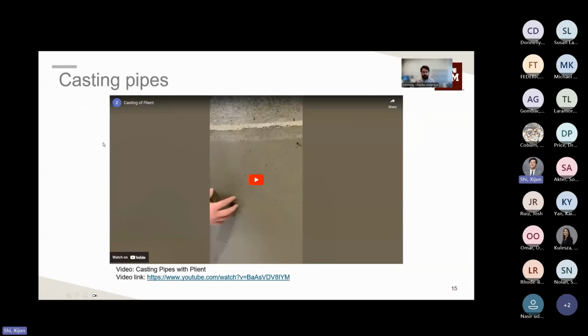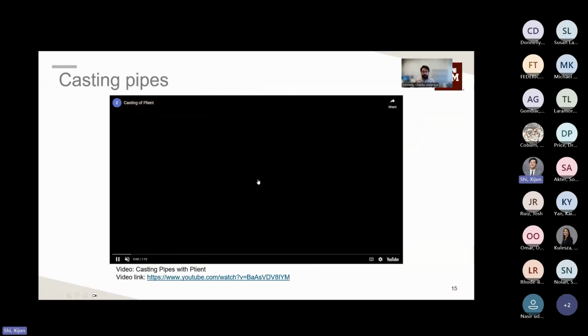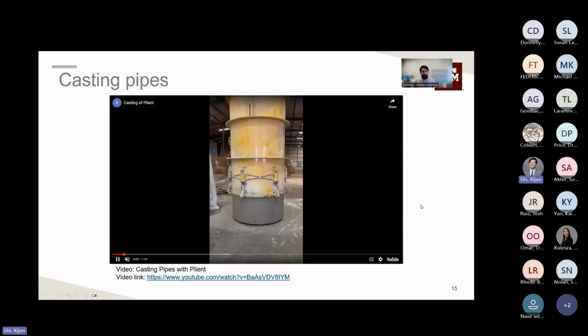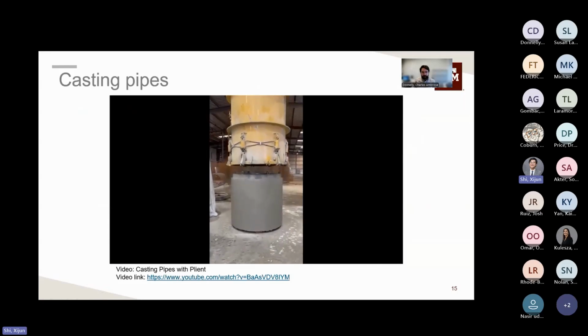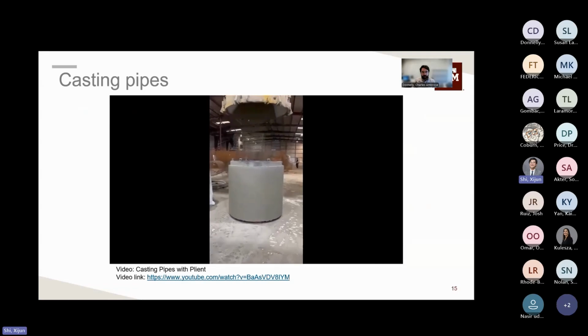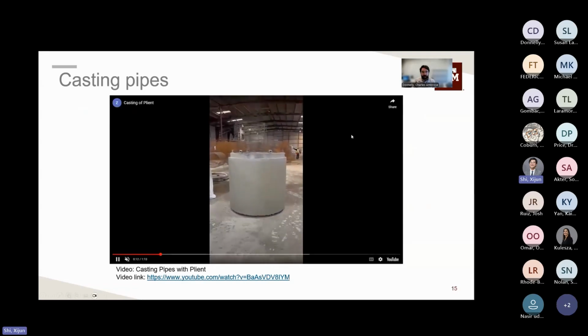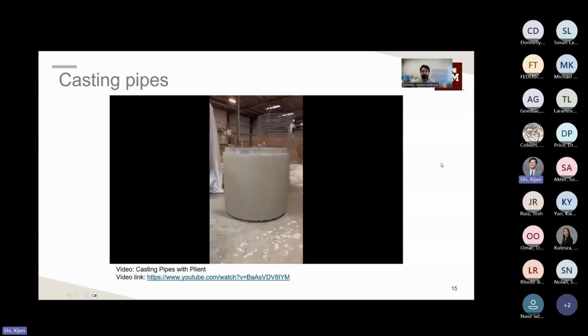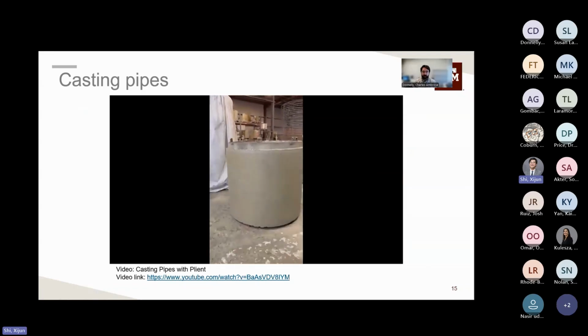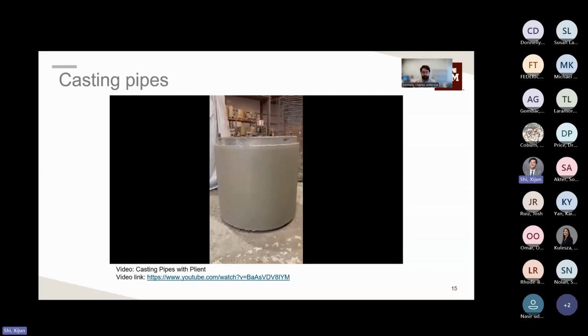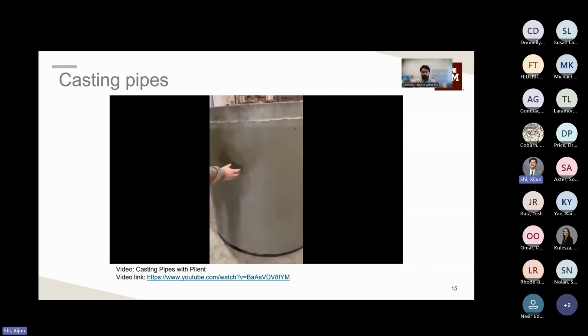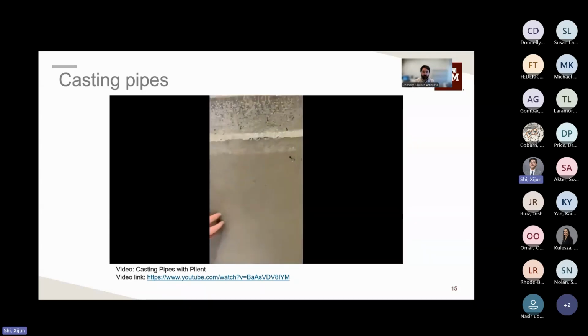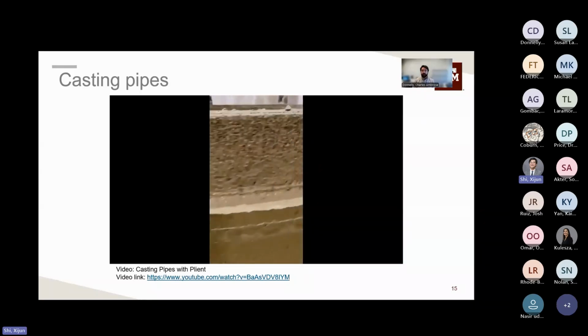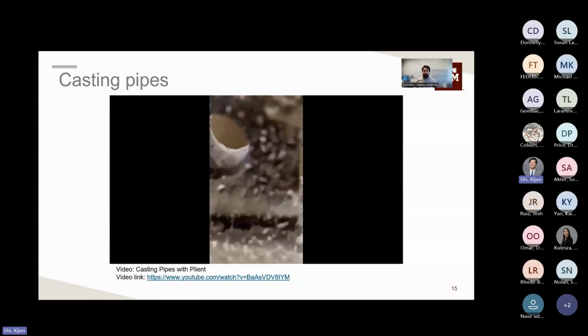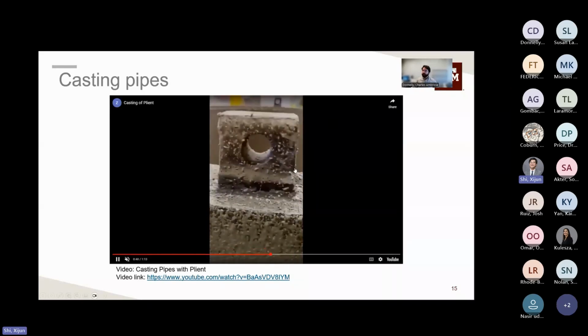Here's a neat video of the dry cast method of the pipe. So this pipe is being constructed with the Plient fibers integrated in. And as you get closer, we'll see that there's seamless integration of the fibers. And actually kind of cool is in the background, you can see the typical cage or mesh that they would use for the pipes, which are eliminated by using the fibers. And you can see that there's no fibers on the surface. It's a stable construction, and you don't have any fibers sticking out or anything like that. It was able to fully disperse and integrate into it. So in this sense, Plient fibers were a huge success with using these pipes, and shows that it can be easily integrated into that construction process.